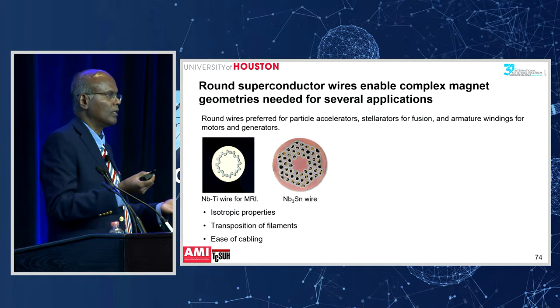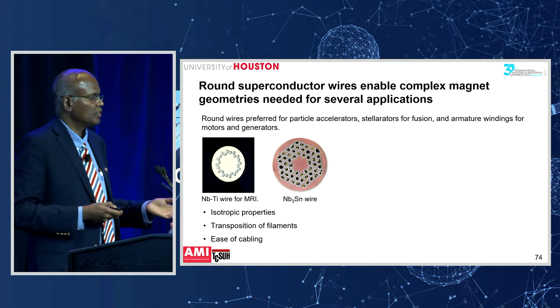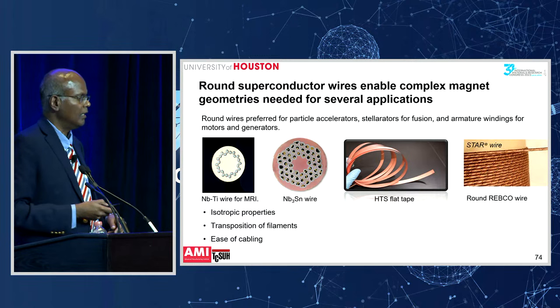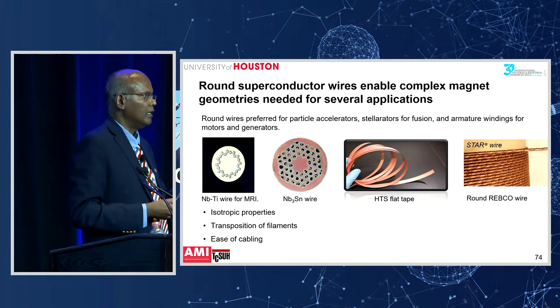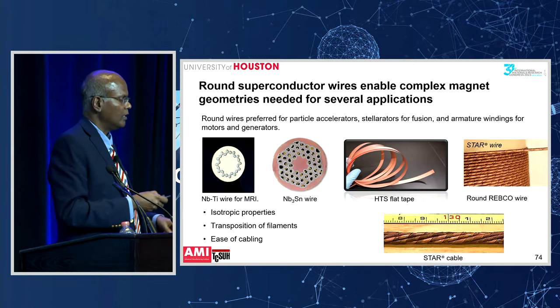So unfortunately, our tape is not round, it's flat. However, we have developed methods, in this case a method called star wire, where actually this flat tape, and not any tape but a specially made tape, is converted into a round wire. And that can be made into a cable also, and this is a star cable. So those kinds of methods also need to be developed.